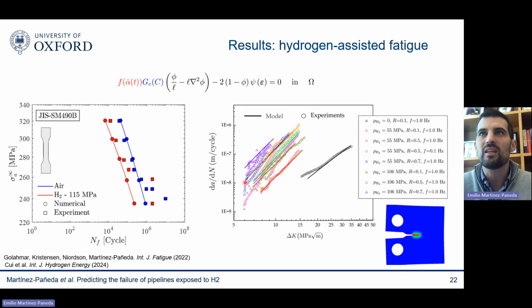Here you can see data from Sandia that have been obtained for different hydrogen pressures, for different load ratios, for different frequencies. And you can see that with the model, we can do this kind of virtual fatigue tests, and we can see the crack growth rates, and we can compare against experiments, and you can see that we get a very nice agreement. So for every condition that we consider, every different load ratio, frequency, pressure, whatever we threw at the model, it was able to predict. And I emphasize, there's no recalibration involved here.